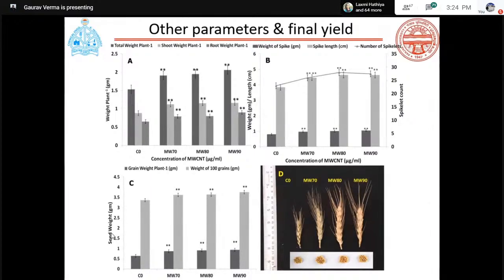And with pleasure, I would inform that we found an enhancement in the seed weight and also the seed count, or the grain count. And this was really encouraging because the whole exercise was successful without having any damage to the DNA, and ensuring that the carbon nanotubes do not enter these grains which you consume afterwards.